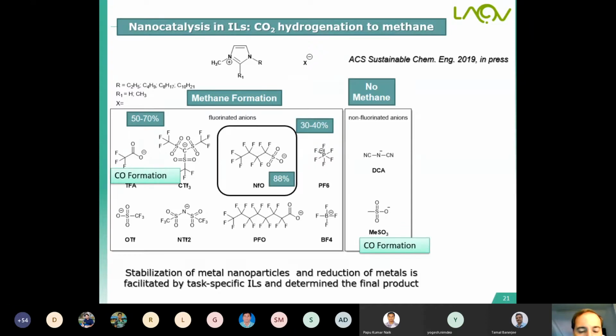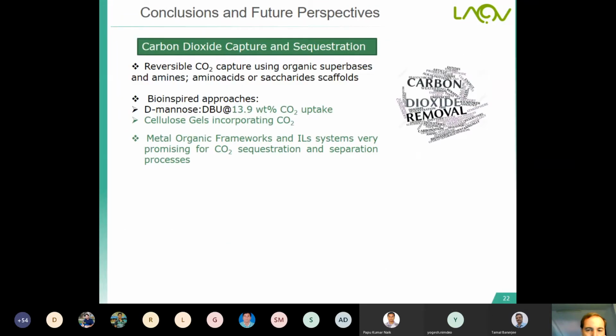The stabilization of the metal nanoparticles and the reduction of metals is facilitated by the task-specific ionic liquids and determines the final product. Okay, in this part, I already showed you carbon dioxide capture and sequestration, the reversible concept using organic superbases in the presence of amines, amino acids, saccharides. It's possible to use a bioinspired approach, a competitive process using D-mannose and DBU and cellulose gels incorporating CO2, but it's also possible to combine metal organic frameworks and ionic liquids for that.